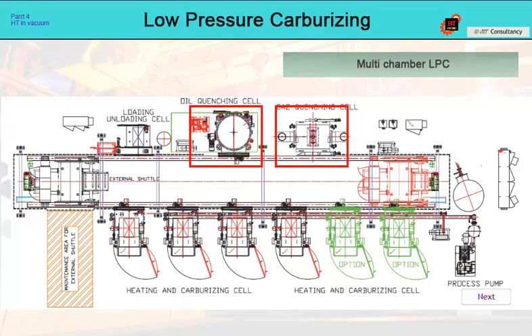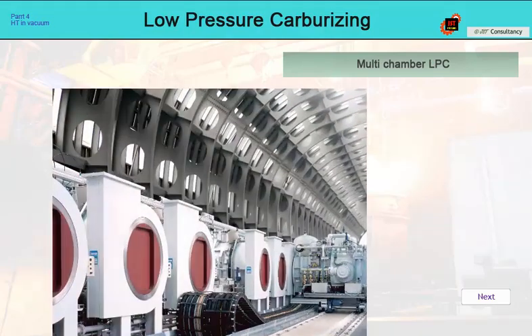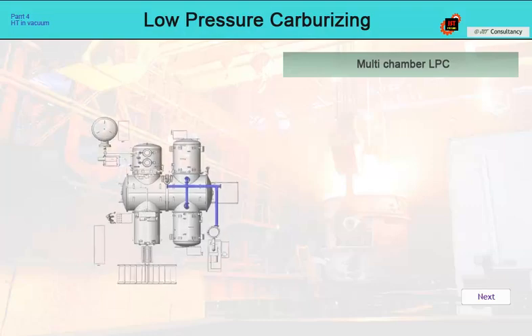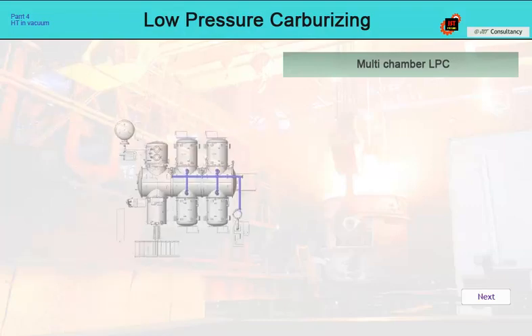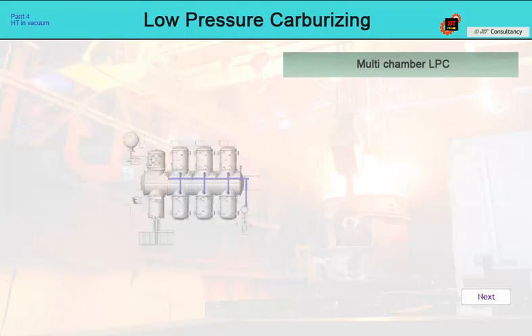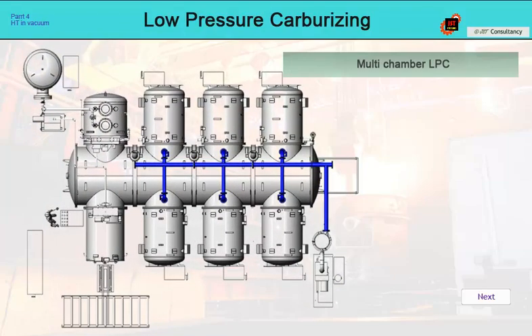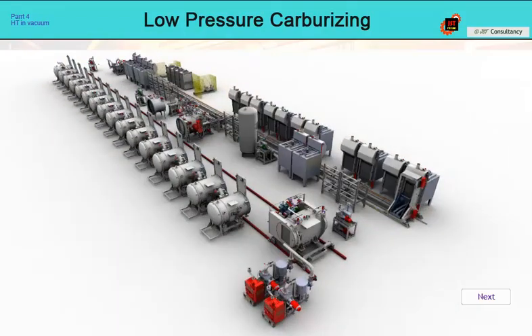In this case, loading and transfer of the batch is carried out via a transport system without a vacuum tunnel. In the case of ECM, the batch is fed after heating into a special chamber for quenching in a gas stream or in oil. The specialty of ALD is that this transport module is also a module for quenching up to 20 bar of nitrogen or helium. All these systems are fully expandable. We can therefore start with a minimum number of heating cells and gradually add more according to the increasing capacity needs.